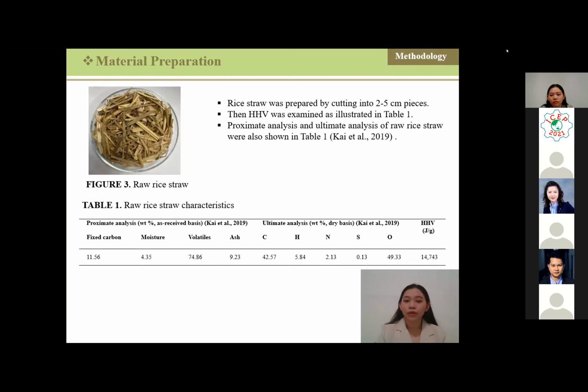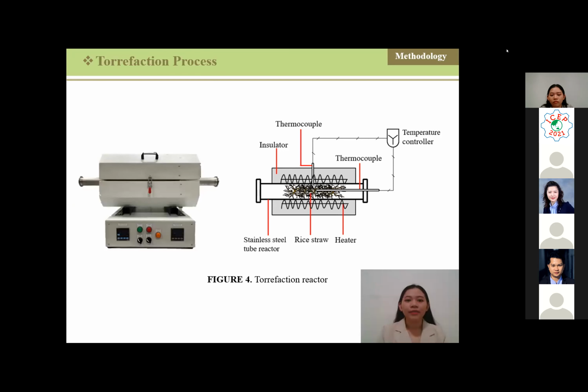And this slide is about methodology. Rice straw was prepared by cutting into 2.5 centimeter pieces. Then the high heating value was examined, as illustrated in table 1. The instrument used in the experiment is a fixed bed reactor. It is made of stainless steel, having 50 mm outside diameter and 1000 mm length. The temperatures were measured and controlled by a K-type thermocouple and a proportional integral derivative temperature controller.